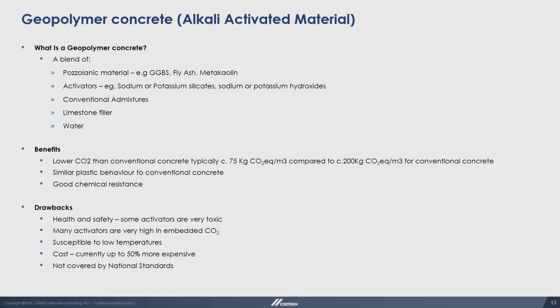In fact, they're probably a scale 5 to 6 times higher than you get in cement, but you're using a much smaller amount of it to activate the material. But nonetheless, you can get down to possibly below 70 kilograms of CO2 a metre, compared to round about 200. Mike used a figure of 208, which I would agree with. Typically for a blended cement concrete, you'd be round about the 200 mark. So, they do offer a significant reduction on what might be considered a conventional concrete.